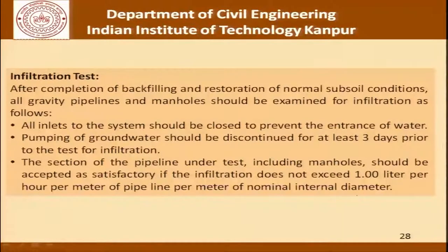As far as the infiltration test is concerned, after completing the backfilling and restoration of normal subsoil conditions, all gravity pipelines and manholes should be examined for infiltration as follows. All inlets to the system should be closed to prevent entrance of water. Pumping of groundwater should be discontinued for at least 3 days prior to the test for infiltration, and the section of the pipeline under test, including manholes, should be accepted as satisfactory if the infiltration does not exceed 1 liter per hour per meter of the pipeline per meter of nominal internal diameter. So, infiltration is basically the kind of water coming into the pipes from outside. And here is the requirement, which could be 1 liter or whatever number you may decide, but the procedure is as indicated here.